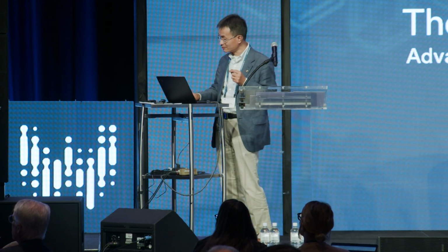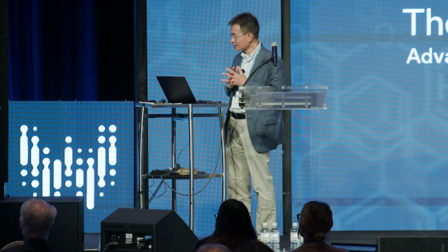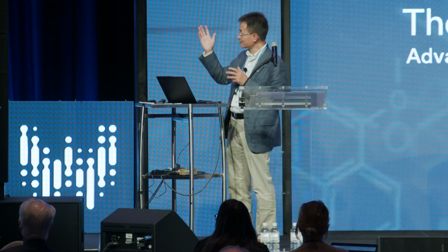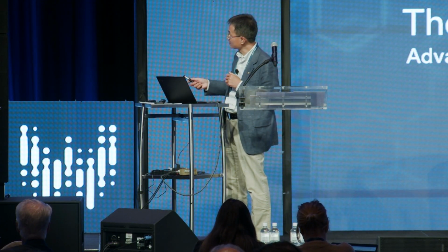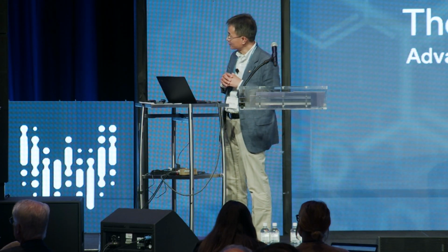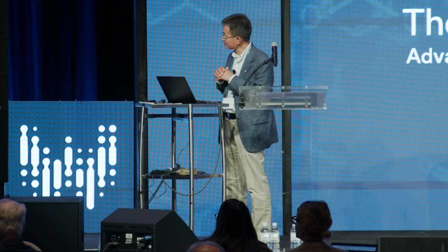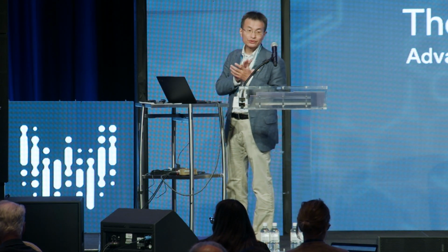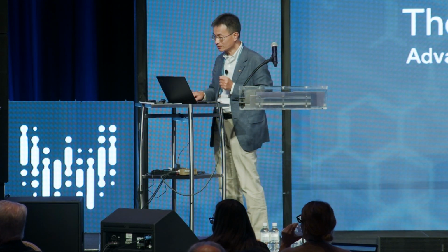As I mentioned, bulk silicon is a thermal conductor. It's traditionally not considered a good thermoelectric material. But here, this low-dimensional silicon nanostructure offers the potential to make low-cost thermoelectric material that can recover waste heat. That eventually led to a startup, Alphabet Energy, that scales everything up. With this thermoelectric energy conversion, you can convert waste heat into electricity. Typically, with these thermoelectric generators, you can recover 2 to 3% of electricity from the waste heat. So that's the second story, on the size-dependent thermal conductivity of these one-dimensional nanostructures, which led to the development of a new type of thermoelectric material.